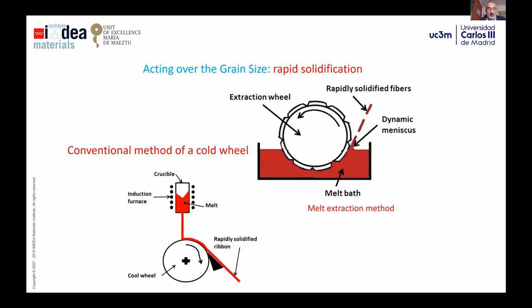Of course, you also have the rapid solidification methods, in which you put a melt bath in contact with a wheel at a very low temperature, and then the solidification speed is in the order of 10,000 degrees per second, or even higher. In that case, you get fibers that can be converted by milling into powders with a really fine microstructure, and sometimes even amorphous microstructures. In that way you can obtain powders that can be used to develop really advanced materials.